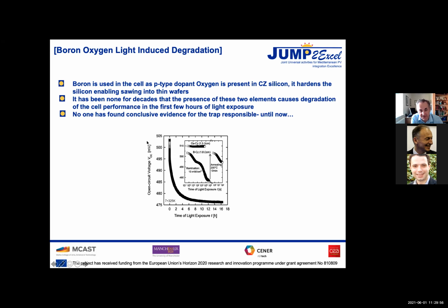So I haven't given it an attribution, but it's Brett Hallam at the University of New South Wales. And he's looking at, in this case, he's represented it by the open circuit voltage, and the open circuit voltage goes down as we go through the cell, and that is an indication of degradation. And there's an even neater result here. If you do it on a log scale, you can see that it seems to have two rates, and that's well established. There seem to be two defects at least involved, two forms, two states. We think probably three states to the defect. So it's a defect that's changing its state, probably negative U as we call it in defect science.